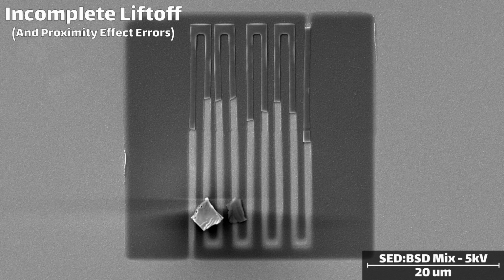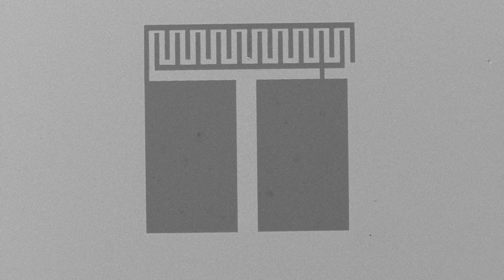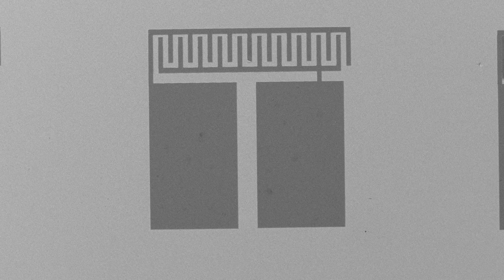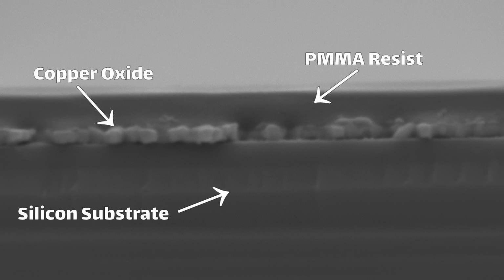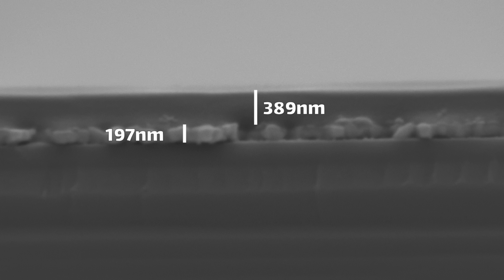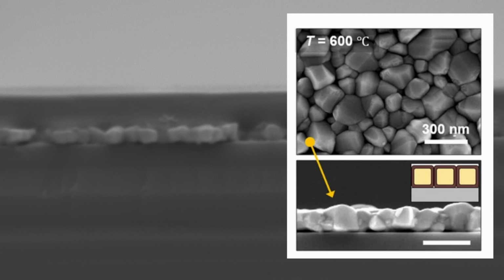But if all goes well, you should get a nice, clean liftoff and have patterned electrodes left behind. So I forgot to mention that in these cross sections, we can also see the copper oxide layer really clearly. There's basically a single layer of large copper oxide grains sitting on top of the substrate. And this is really cool because it mirrors basically what the papers show, although the photos aren't quite as crisp as what's in the Nature paper. But yeah, super cool to be able to see this single layer of grains rather than really fine copper grains.